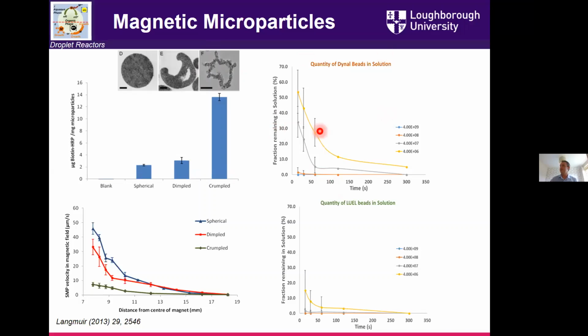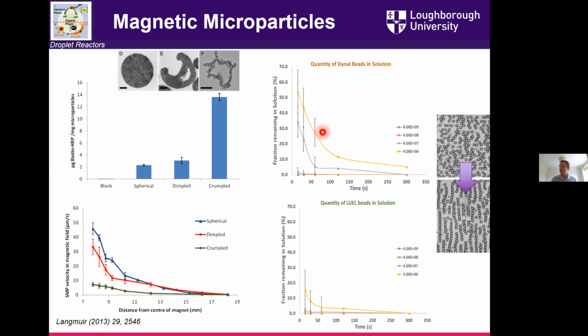And so these are some commercially available examples of beads that you can buy. These are some examples that we can make. And if you look at the time axis here versus the fraction left in solution, not only is it about the size of the particle and the shape, but it's about how much you add. So these are all the numbers of particles per mil, and the speed at which they come out is dependent upon their concentration as well, because of the way in which they move. And we were doing a lot of work on optimizing this so that we can incorporate these into automated analytical processes that would allow us to extract the analytes of interest.